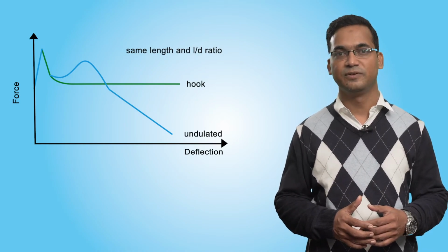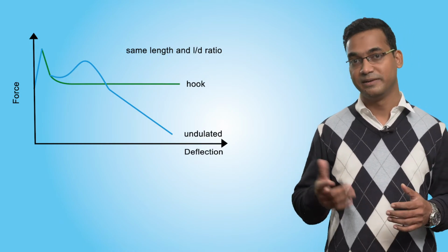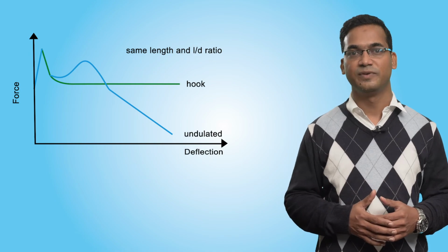This is essential for the ductile performance of the concrete matrix, because if the fibers get too well anchored in the concrete, for example crimp fibers, then this leads to snapping of fibers or local crushing of concrete, leading to a brittle nature of failure of steel fiber reinforced concrete. It is therefore advisable to choose a fiber which is hooked end and just right dimension to fulfill the requirements.